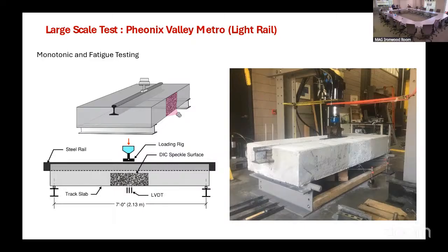And then in the meantime, we did image analysis where you measure the crack formation in the sample. We put strain gauges on the slab, top and bottom, and then we collected the data. We have a report available. There are papers that are coming out of the work. And the whole idea is to make sure that this technology is used throughout the world. And it is being used throughout the world. Recently in Toronto, they have adopted it for the same type of approach for the tunneling and the track slab.